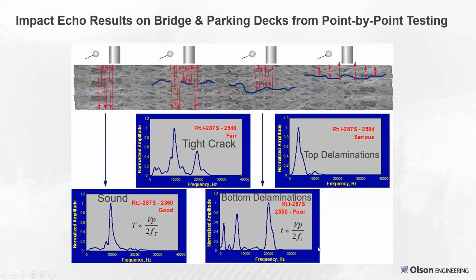As a quick overview of the type of damage you can evaluate, in a sound area, this is basic impact echo. When you impact it, the sound waves travel back and forth between the top and the bottom, as Larry discussed earlier, and you get a thickness that indicates the full thickness. If you have partial cracking, you might get echoes from both the overall thickness and from the shallower crack. In an area that's only cracked, you're only going to see just the cracking area.